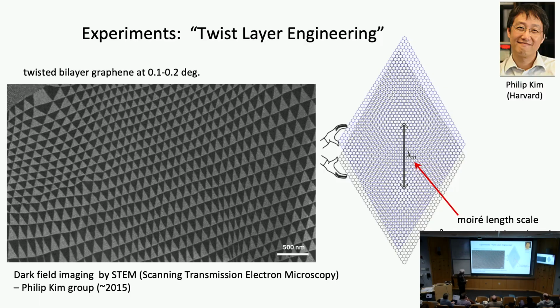And what you see is this kind of superlattice, the Moiré length scale pattern, where in some regions the atoms on the two layers perfectly match each other, top and bottom, so you can only see one lattice. But in other regions, the two lattices are very much mismatched, and you see this very complicated pattern. So this introduces the Moiré length scale, which is much larger than the atomic length scale, and produces very interesting effects because electrons now have to obey not only the strict periodicity of the atomic lattice in each layer, which is there and unavoidable for the electrons, but they also have to obey the constraints imposed by this additional periodicity, the Moiré scale periodicity. And that's what produces all the exciting additional interesting effects.